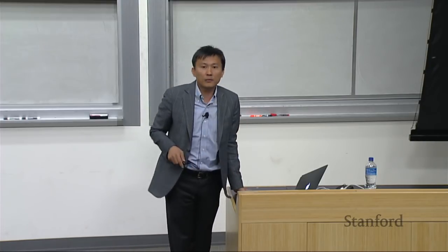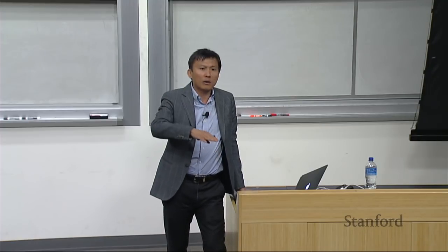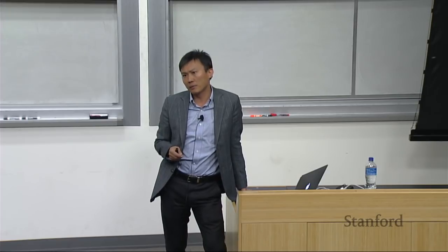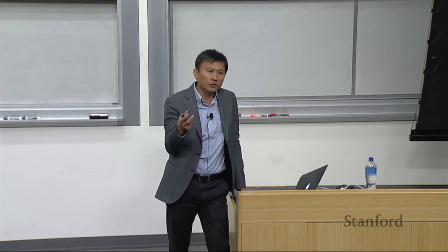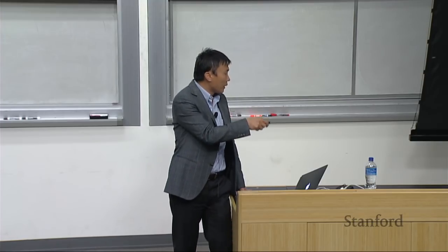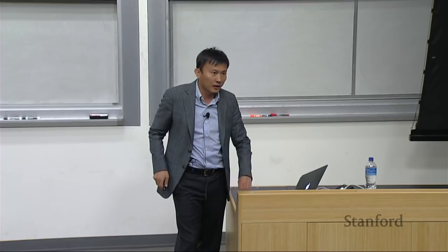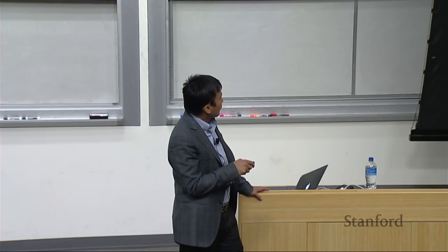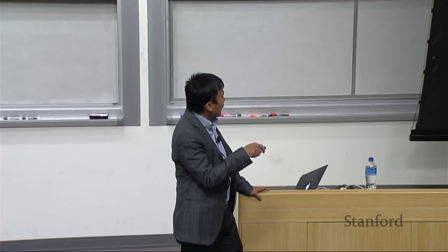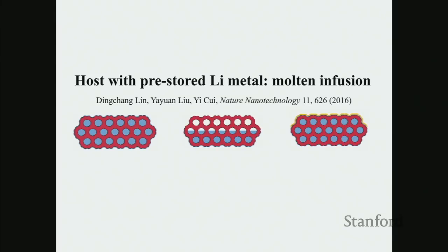And after that, we saw it's not enough, because with this 15 micron lithium plating in and out, it's just too dramatic. We need to build a stable host, hosting metallic lithium inside, together with a few other strategies. Let me highlight this host idea. This was done by a graduate student, Ding Chang, who is sitting right there. We want to build a host, hiding this metallic lithium in domains inside this red color host. If you strip lithium away, this whole structure remains stable and holds the whole volume right there, making it possible to have an interface you can build. And then when you plate lithium, it plates into this host. So Ding Chang developed a very clever concept.